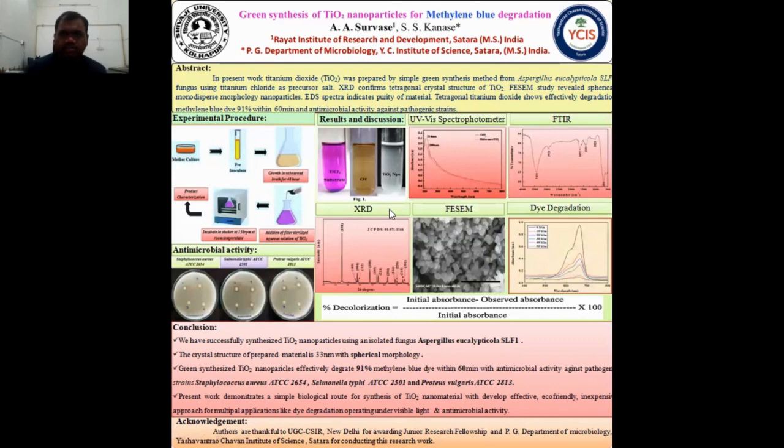We used field emission scanning electron microscopy technique for observing the 3D nature and morphology of nanoparticles. We observed the spherical nature of TiO2 nanoparticles, having a size range below 50 nanometers.